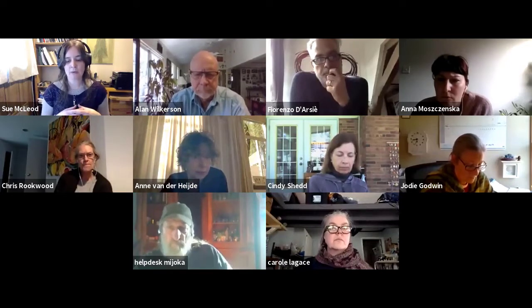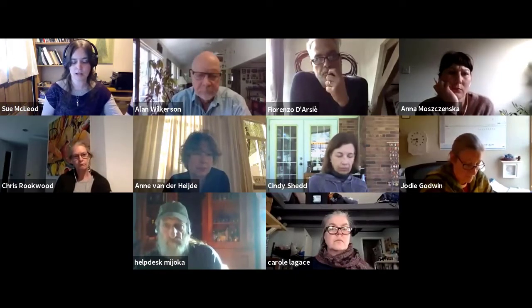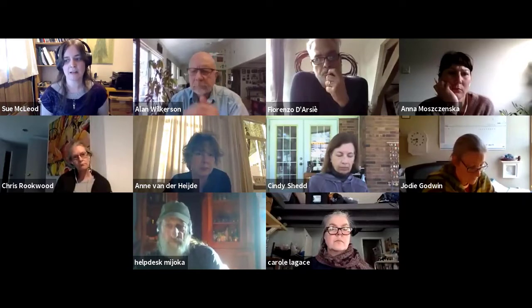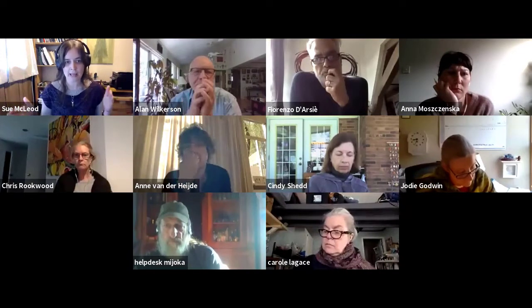But because we have a studio with hundreds of people, this person wants to put slip on this pot and this person wants to put slip on at different stages. So I found that with calcining a little bit of the clay, the slip becomes a little more versatile, where it works on a wider range of dryness.